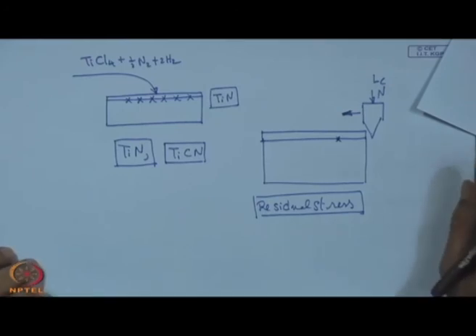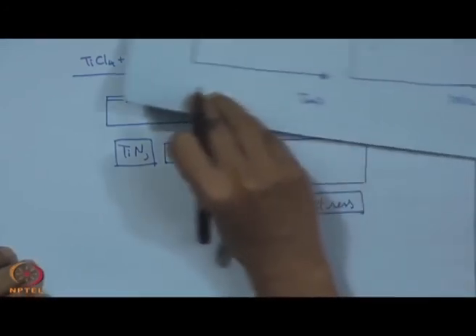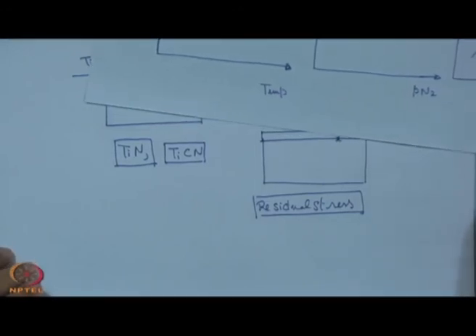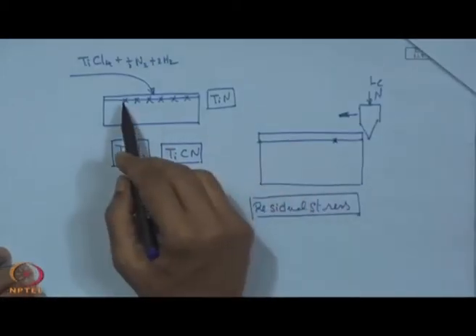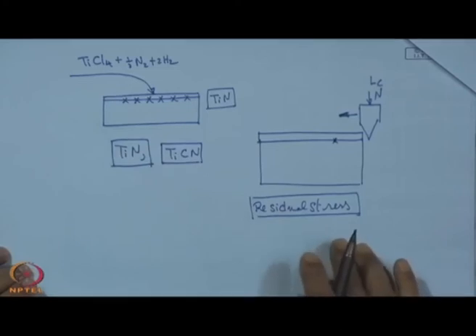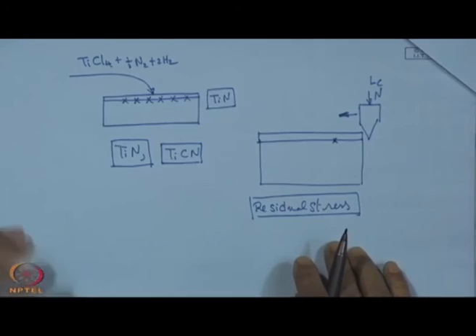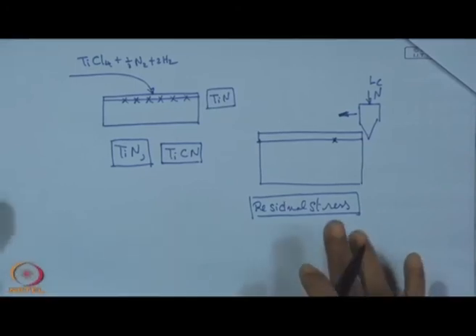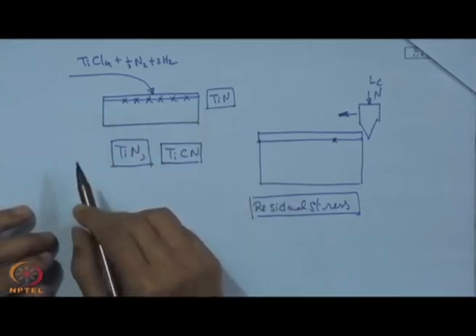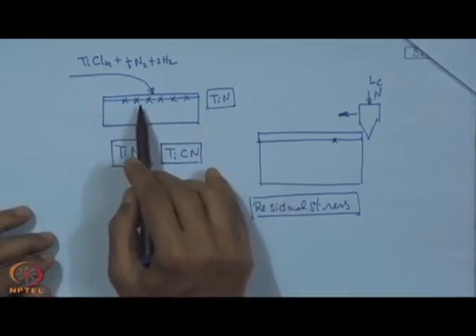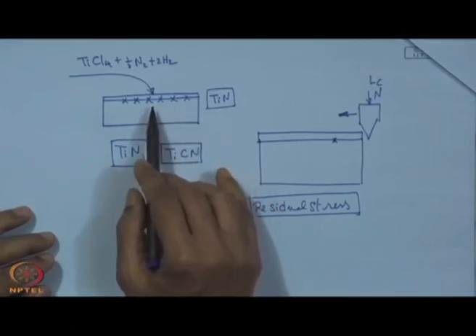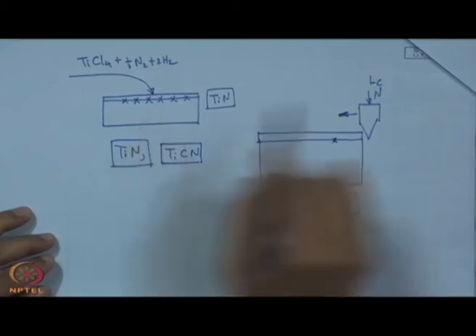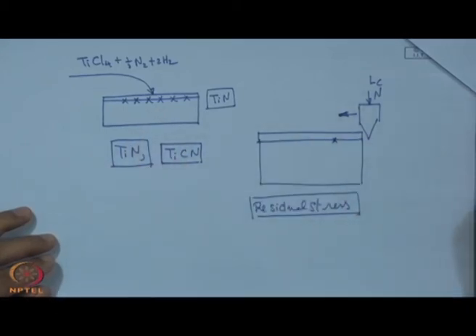Similarly, PN2 and PH2, these are also the partial pressures, and with this partial pressure, exactly what happens? We want to have the reaction here, but because of the high pressure of nitrogen or hydrogen, this can be promoted in the gas phase before the reactants reach the surface. If that be the case, then we can have some flake formation, some voids may form, some dust may form, which is less adherent, and as a result this kind of fall of the critical load may be observed.